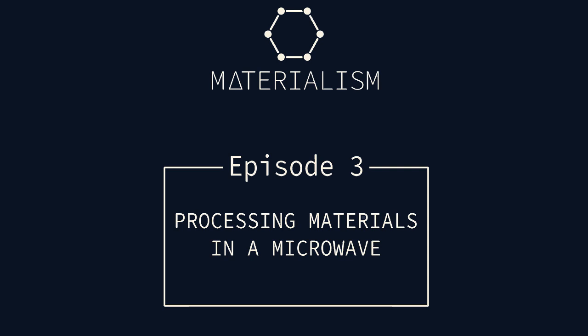This creates a gradient between the surface and the center of the object, and this can create inhomogeneous microstructures near the surface. On the other hand, when materials are heated up via microwave, most of the absorption is happening in the core of the material and less on the surface. And that can lead to extra heating in the core, which can also mean inhomogeneous microstructures due to a temperature gradient. One solution to both of these problems is to use what's called a hybrid model.